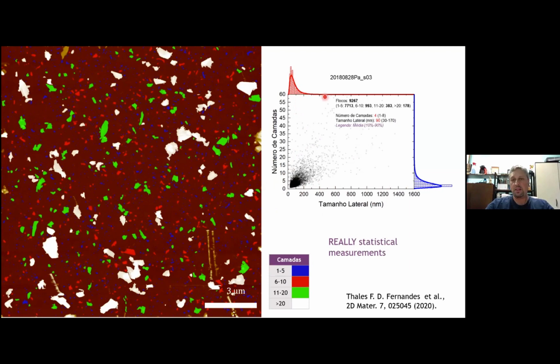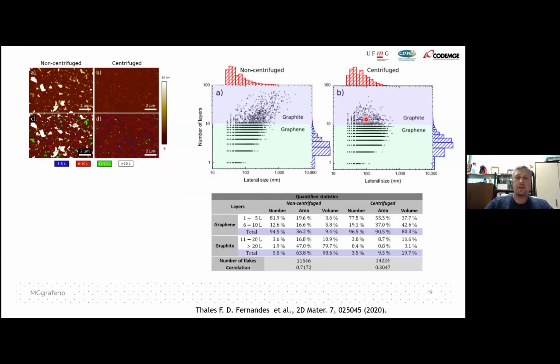Here we can make these histograms of number of layers and lateral size. And for this sample here, we measured like 9,000 flakes. And we have all the statistics about how many flakes are between 1 and 5 layers or 6 to 10 layers and so on.